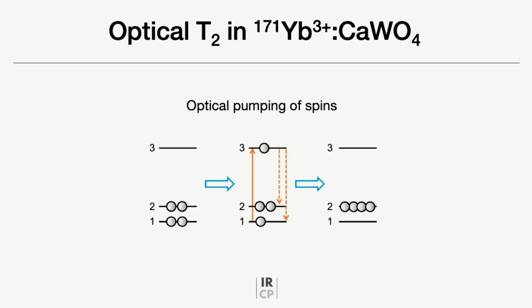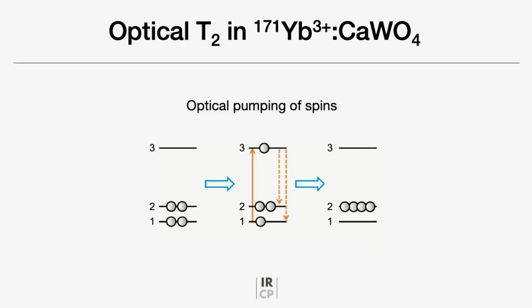When the ytterbium ions arrive here in the excited level, they can relax by spontaneous emission, either to level 2 or level 1. If they relax to level 1, they can simply be re-excited by the laser, and we start the cycle again. But if they end up in level 2, they may simply stay there for some time. So if we shine the laser long enough, and the lifetime of level 2 is long enough too, you end up with all ions in spin level 2, and this is what I call polarization of the spin, so that we have all spins in the same level.